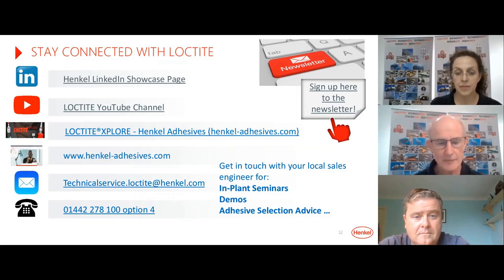I think generally speaking, for very large parts, people really think they might need a very strong adhesive. But if you've got large bond areas like that train floor, when they first came to us, they said they wanted a really strong epoxy for that. We said, well, no, you don't. You've got plenty of bond area there. You can get away with an adhesive which has only got a strength of, say, 2 to 3 megapascals, and it's more than strong enough because you've got so much bond area. So it really does depend on the application as to which adhesive we would recommend.